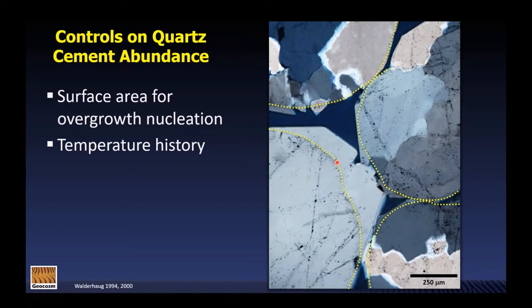So when the overgrowth nucleates and begins to grow, it actually needs to have a pre-existing quartz crystal for that dissolved silica to nucleate on and for that crystal to continue to grow. And so things that will affect the amount of surface area that's available for quartz overgrowth to form would include, of course, the proportion of the rock that's made up of quartz grains, the grain size, smaller grains have higher surface areas per volume compared to larger grains, and also very importantly, the occurrence of very thin coatings on the surfaces of grains, for instance, of the mineral chlorite, or actually of many different types of substances, can also reduce the nucleation surface area and have a big impact on quartz cementation rates.